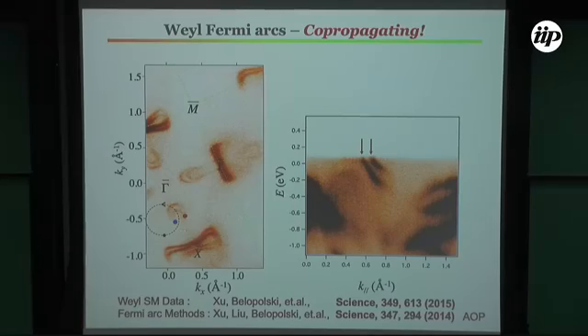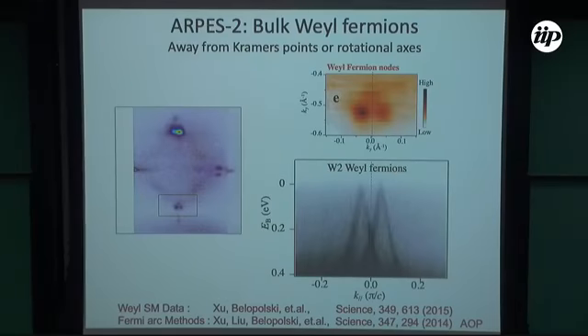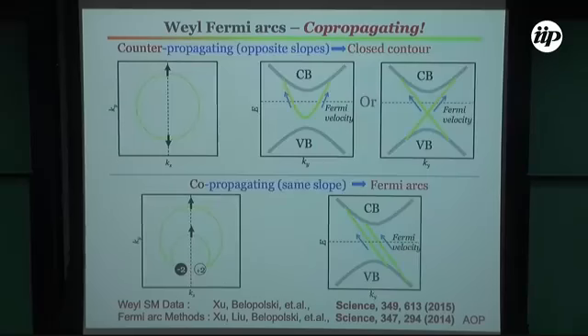So we take an unconventional cut. We take a loop cut on the surface states, and we see that in the energy axis, they're co-propagating. They're not merging. And the fact that they don't appear here is not an image plot issue. This can be repeated. Now, if this is the case, then we should be able to find the bulk counterpart of what was on the surface. So what happens in the bulk?